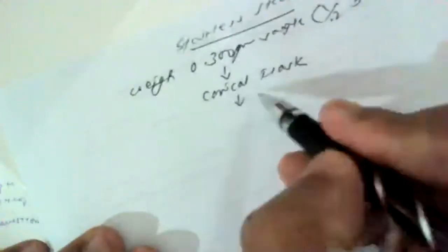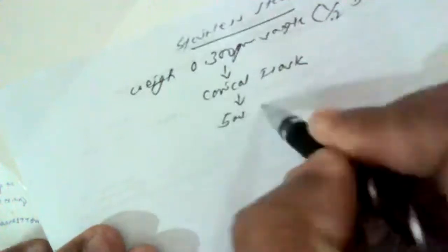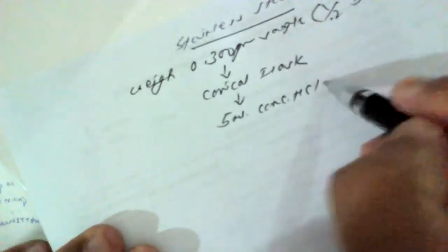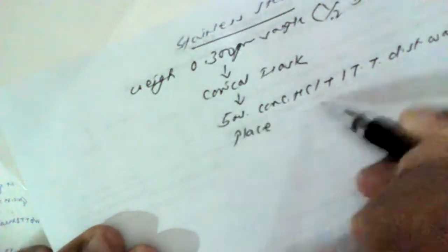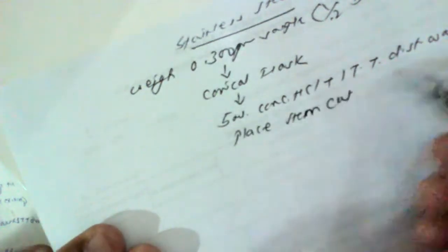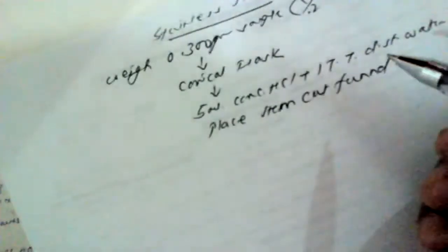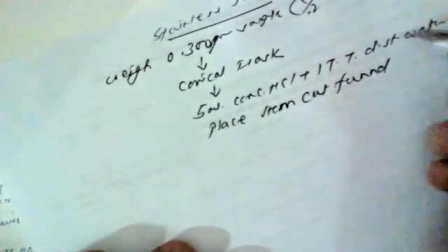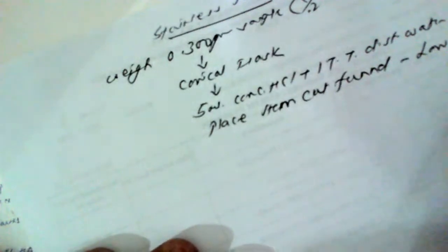Now, to estimate this iron and chromium, first of all, we have to weigh the sample. That means half part of the razor blade that we have to take, and this razor blade is to be taken in a conical flask. To this razor blade, we have to add 5 ml of concentrated HCl solution, then 1 test tube of distilled water, and we have to place a stem cut funnel. We know the funnel that we are using in laboratory, it is known as a stem cut funnel, and we have to heat this content on low flame.